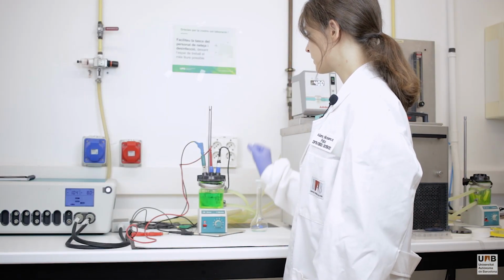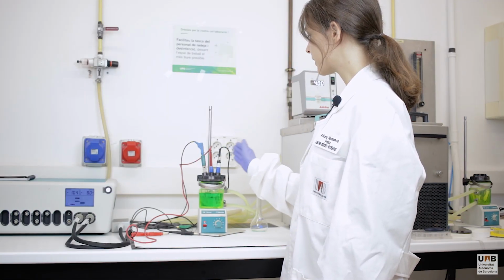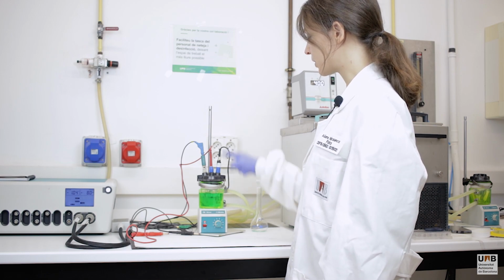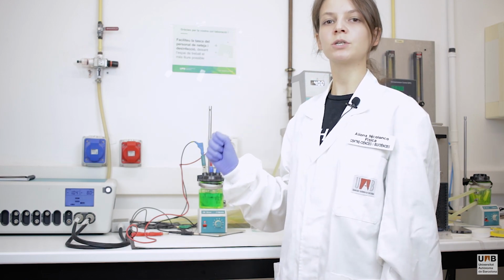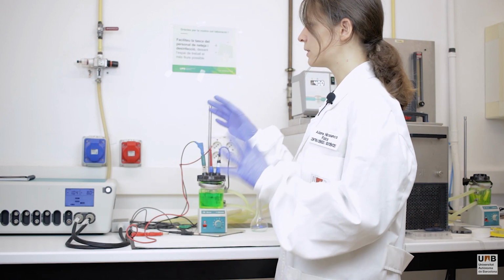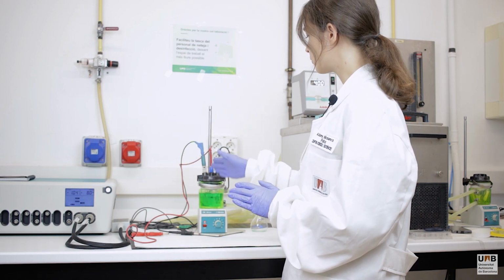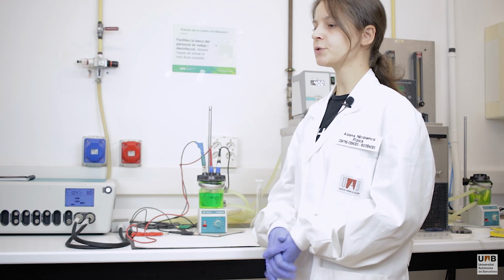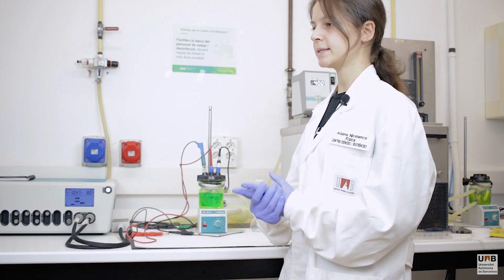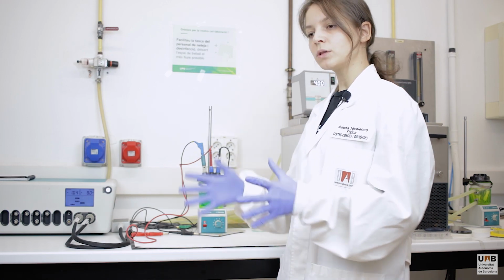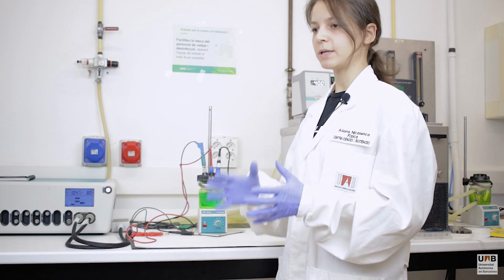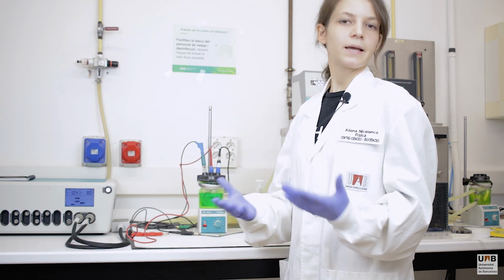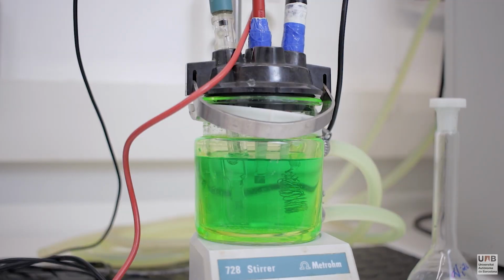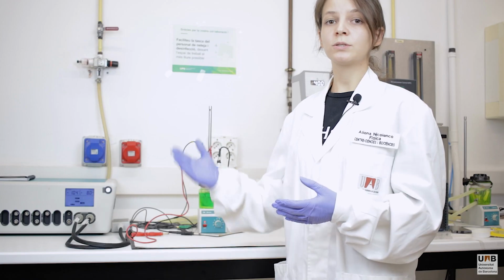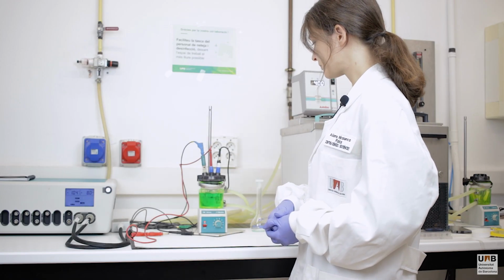During the experiment, the current primarily occurs between the working and counter electrode, while the potential at the working electrode is measured with respect to the reference. So when the power is turned on, the working and counter electrodes gain charge. So our working electrode is polarized negatively. So all the positively charged ions from the electrolyte will be attracted there and then reduced. So nickel 2 plus ion will be reduced to nickel 0 and deposit on the working electrode.